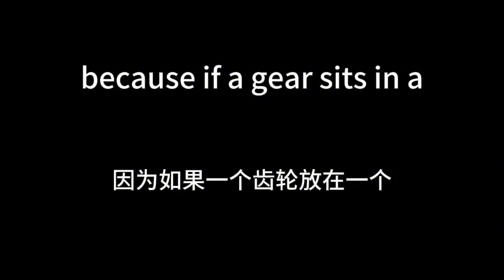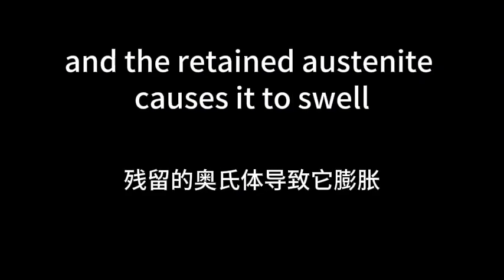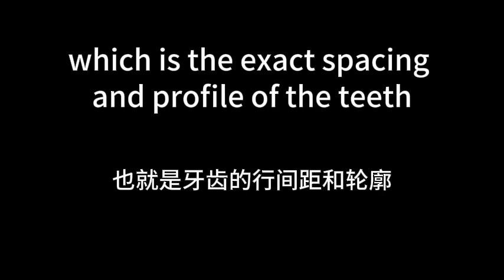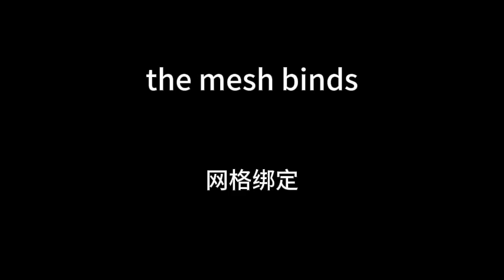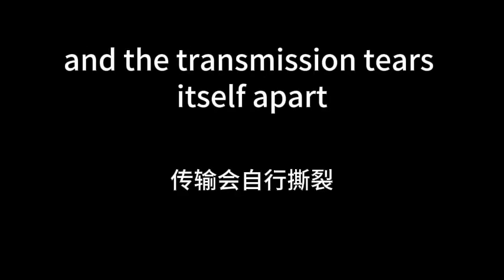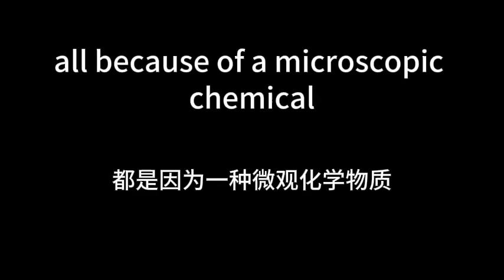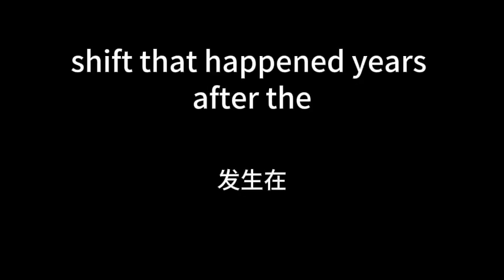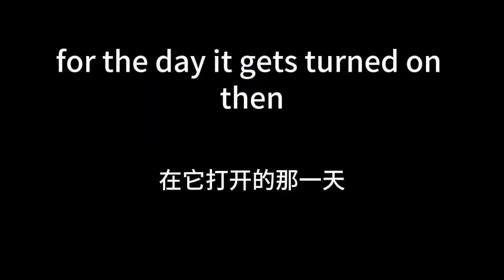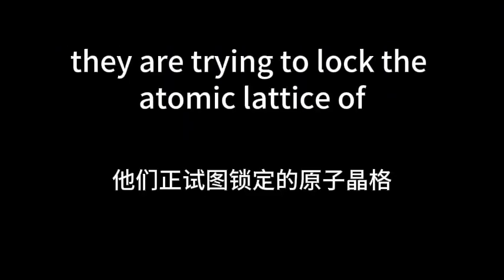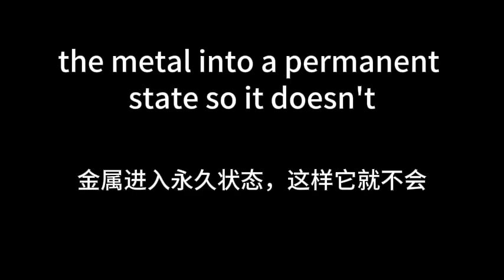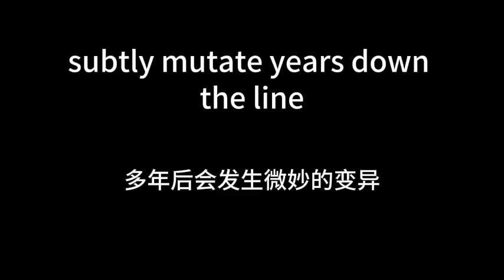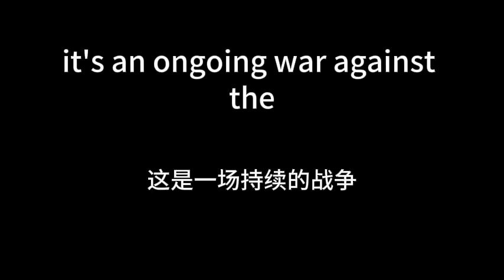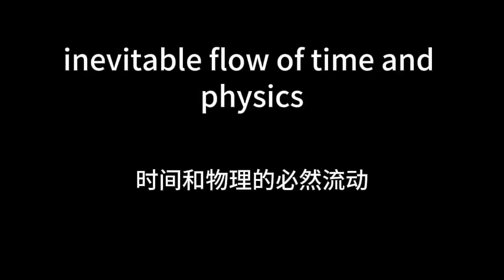Because if a gear sits in a transmission for 2 years and the retained austenite causes it to swell, the pitch, which is the exact spacing and profile of the teeth, drifts. Exactly. The teeth get thicker, the mesh binds, the friction spikes. And the transmission tears itself apart. All because of a microscopic chemical shift that happened years after the manufacturing was supposedly finished. Engineers aren't just designing a machine for the day it gets turned on then. They are trying to lock the atomic lattice of the metal into a permanent state so it doesn't subtly mutate years down the line. It's an ongoing war against the inevitable flow of time and physics.